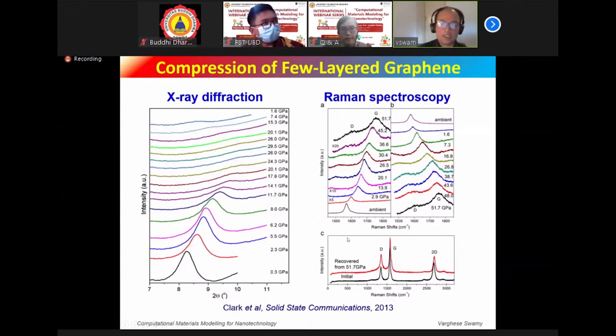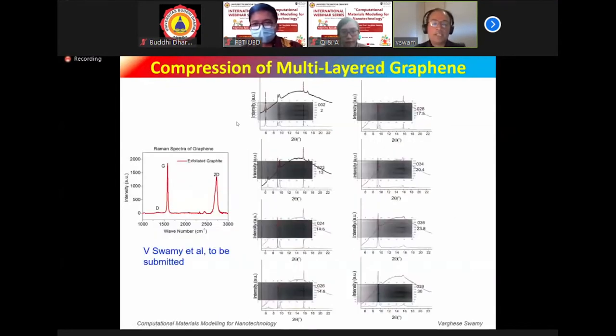This was published by Clark et al. in Solid State Communications in 2013. Under compression, it converts into another crystalline structure. It's more like a diamond, most likely, because it's a very stiff material, very difficult to compress, and it's not disordering. So we were looking at simulating this work sometime in the near future.